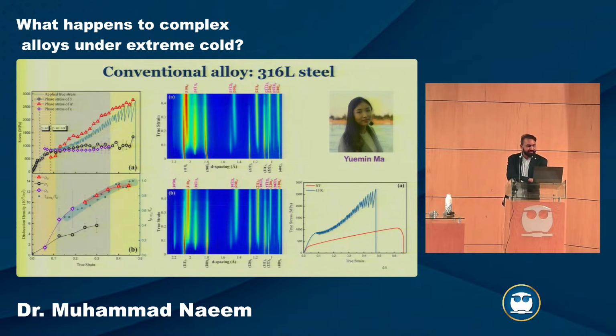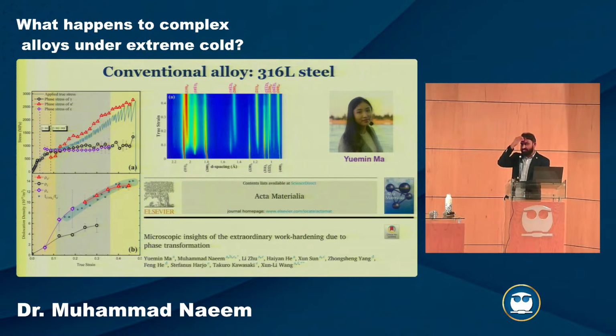So these are phase stresses for FCC, HCP, and BCC. BCC is the one which is contributing more to this high strain hardening, and also the dislocation density is much higher. You see FCC is these black ones, and much higher in BCC over here, these red ones, and HCP appears and then disappears. So we also tried to understand the mechanism, how FCC to HCP to BCC transformation is happening. This was published just a few months ago, I think 3-4 months ago in Acta, and it was a very interesting study.